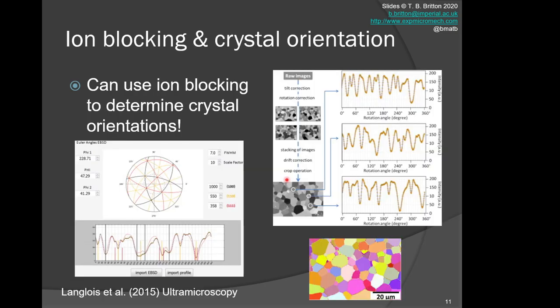This can be useful. There's some really nice work by Langlois and colleagues who developed a method to measure the orientation of crystals using ion blocking patterns. The paper is beautiful to read, but very briefly, they capture a series of maps at different orientations of the crystal. They predict what the expected variation in contrast is with regard to the orientations of the crystals. They match the intensity variations, and you can generate an EBSD-like map with about five-degree orientation variation.